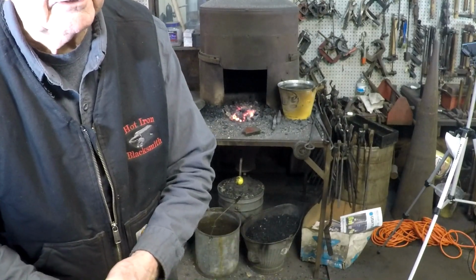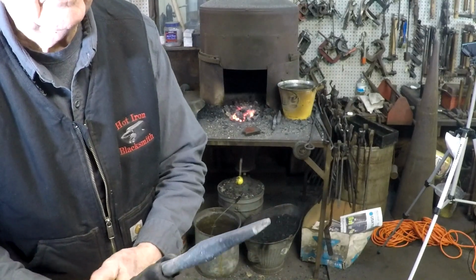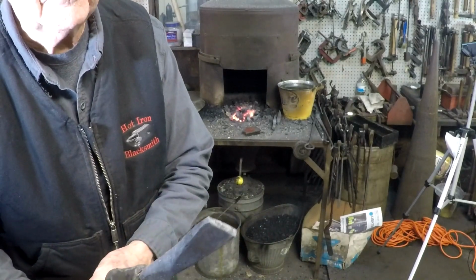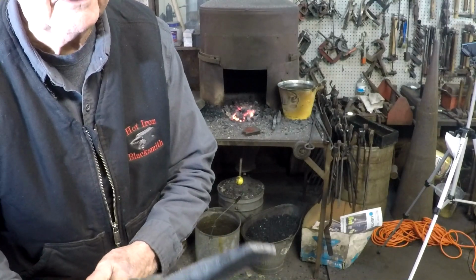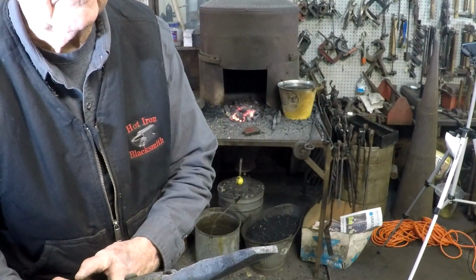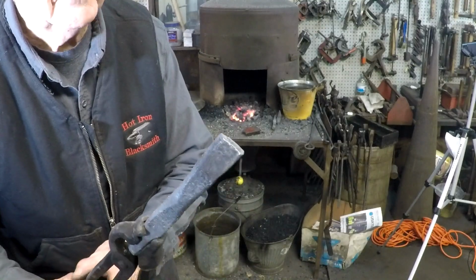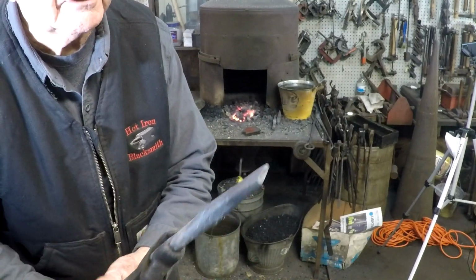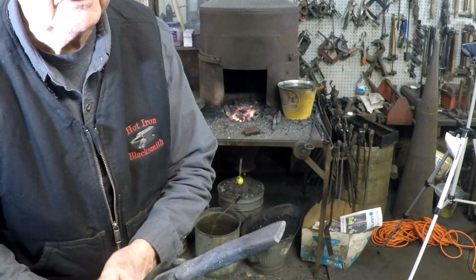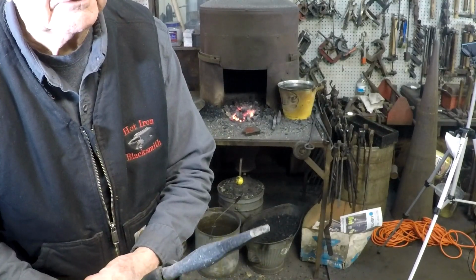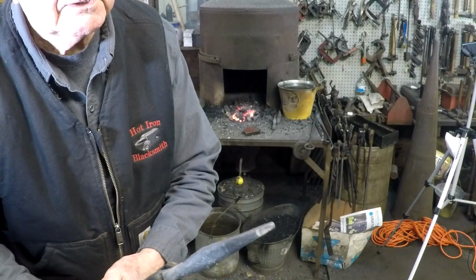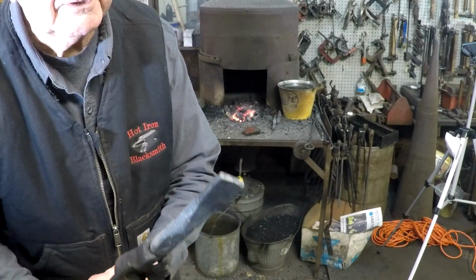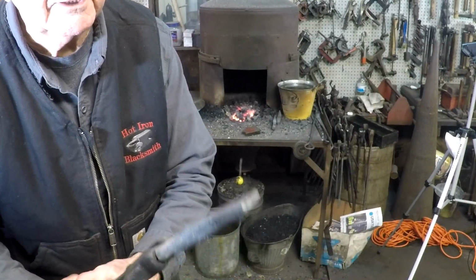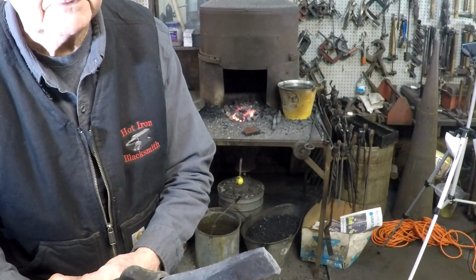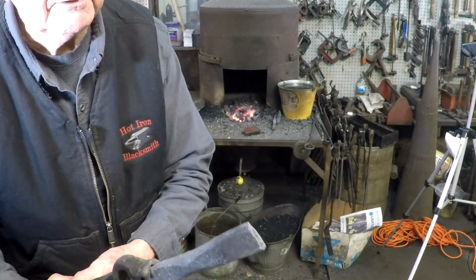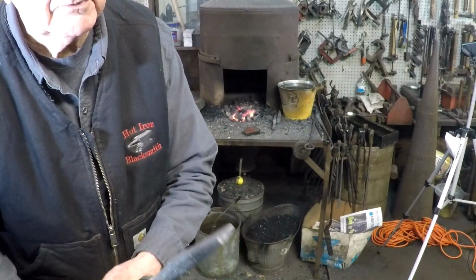Now bear in mind, this piece that I'm showing you here, we have not taken to the bench and filed off the edges. I see the roughness of the hammer marks, and since the very tip of this is hardened, our file is not going to be very happy trying to remove the hammer marks. So we may have to go to our 4.5 inch grinder or a belt grinder on the stand in order to actually remove some of that roughness. But you get the general idea of what we're trying to accomplish in what I'm showing you here.